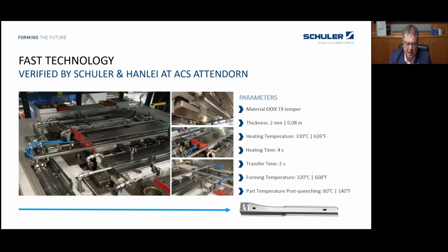It was actually related to the capability of the press, because it's not so normal for a servo press to stay under pressure in BDC. So we had to trick the control system a little bit. Then with our transfer, we could reach a transfer time of 2 seconds. And so we didn't lose much temperature. So the forming temperature was 320 degrees. And after the forming and quenching, the part temperature was 60 degrees Celsius.